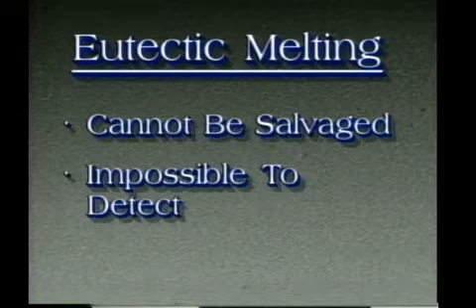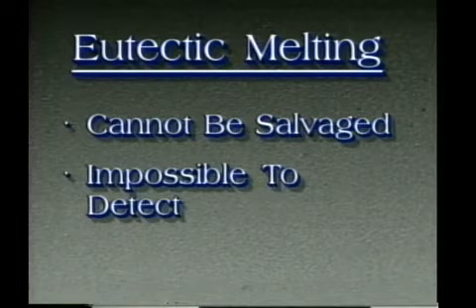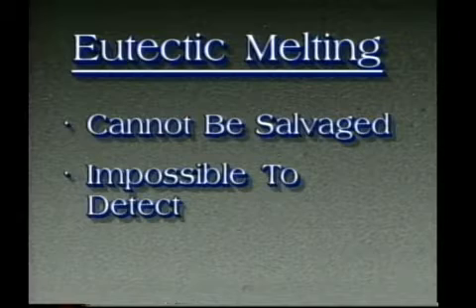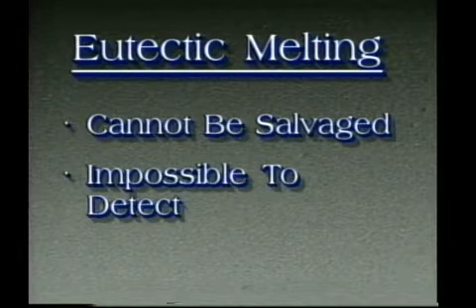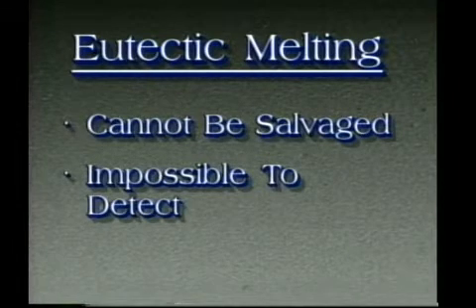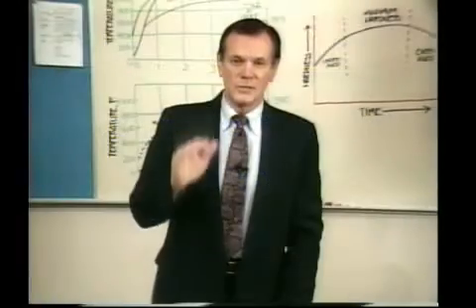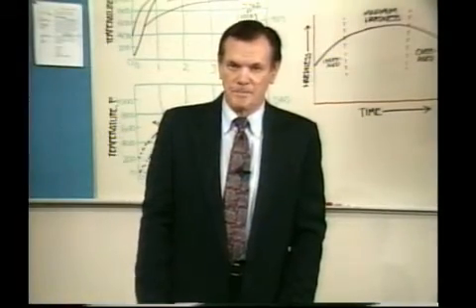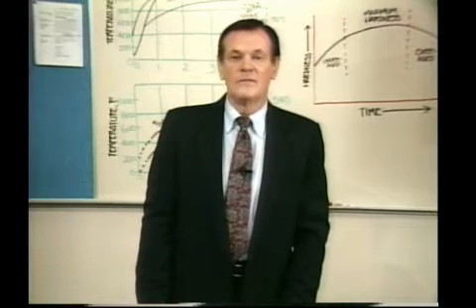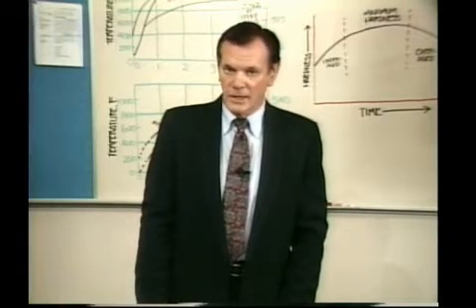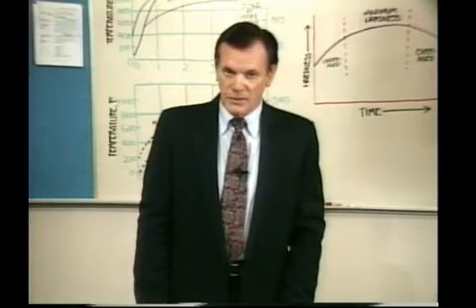Material that has been overheated may achieve a normal hardness after aging, and the effect on electrical conductivity readings is very small. Thus, an inspector may not discover an overheated defective part. Only destructive testing will reveal the condition. If the overheat condition is extensive, tensile tests will show low ductility and sometimes low tensile and yield strengths. An example of an overheated 2024 part is shown in this photomicrograph. The damaged part exhibited an extensive rosette pattern and grain boundary melting in the microstructure.